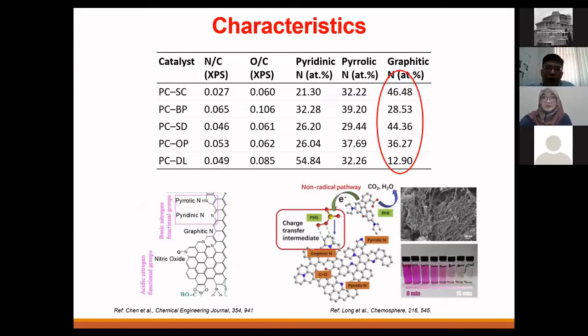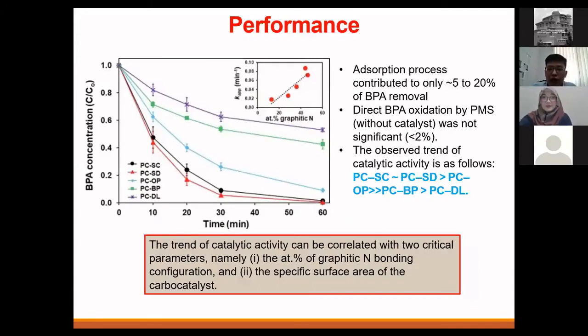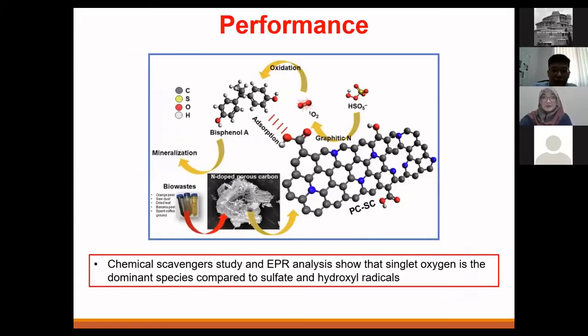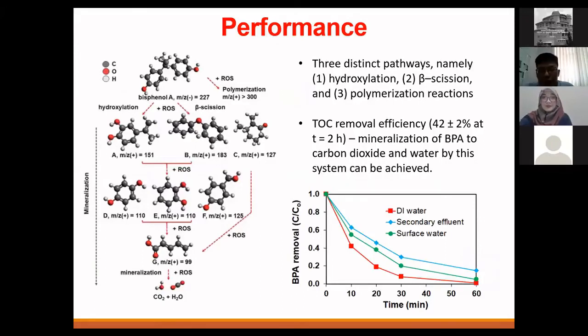Okay. These two are in general lignocellulosic carbon, right? And they give you up to 46 atomic percentage of graphitic nitrogen. So graphitic nitrogen itself is one of the best functional groups for peroxymonosulfate activation. Okay. So to show you some results, as you have higher graphitic N, the degradation of bisphenol A, which we use as our pollutant, is relatively higher with increasing graphitic N. Okay. So just to share with you, in terms of application to the real environment.